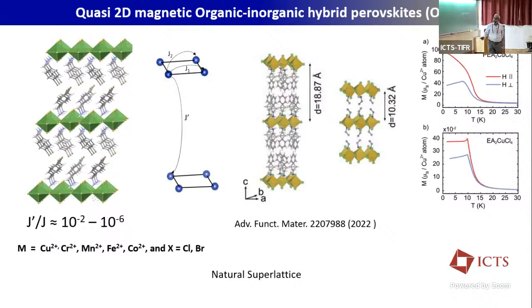What we'll be talking about is not the van der Waals materials, but quasi-2D organic-inorganic hybrids, a family of materials which are quasi-2D. These systems look like this. You have a transition metal ion sitting here, and the ligands, instead of oxides, are chlorine and bromine. And these are the organic layers, and the organic layer spacing is large, because you know that the exchange interaction dies even at 1 nanometer. But here the spacing can vary from roughly 1 nanometer to 2 nanometer. That is why the interplane interaction J prime by J, relative to the intraplane interaction, is roughly of the order of 10 to the power minus 2 to 10 to the power minus 6, depending upon the length of the spacer layer. And you can in fact tailor this spacer layer.